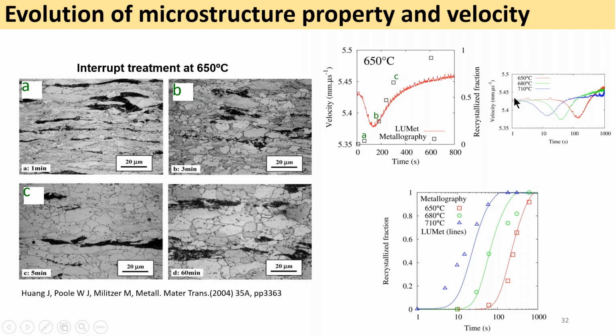We've done this at those three temperatures, and by processing those velocity signals, we were able to acquire the recrystallization kinetics for those three conditions in 3 tests, whereas by microstructure analysis it requires many interrupted tests to acquire this recrystallization fraction. So here it's a very important point with this machine, where we have a really large gain in time for acquiring this type of measurement.